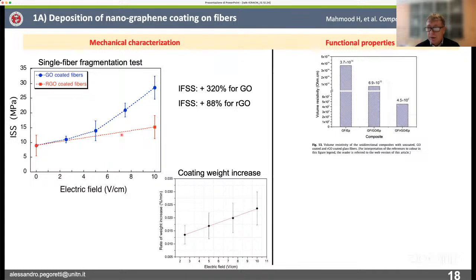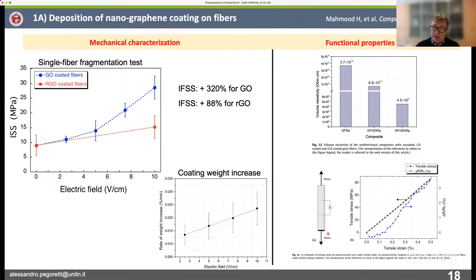A side effect, but a positive one for some applications, is the fact that by using reduced graphene oxide, the resistivity of the composite is decreasing. In particular, if you look at this bar, we reach a resistivity in the composite material which is very low, which means a quite high electrical conductivity, especially in comparison to the uncoated materials. So we move substantially from an insulating to an electrically conductive material. And we test the material under tension, and simultaneously we measure the electrical resistance.